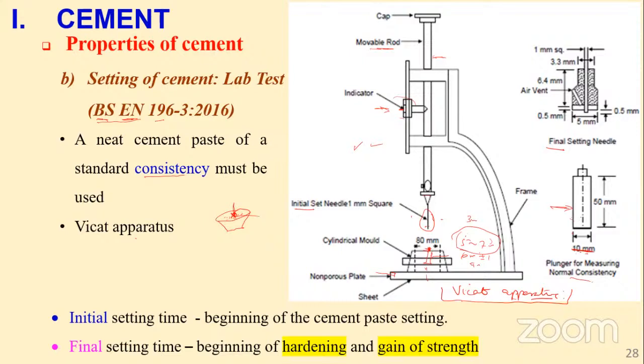Now, once we have prepared a cement of standard consistency, then we move ahead to modify. For initial setting time, we use this small needle here. For the final setting time, the needle is 1 millimeter square, the same needle here. But now we attach this part with some sharp edges here, so that the same principle applies: it rests, and then you release this removable rod. You see how much it's going to penetrate.